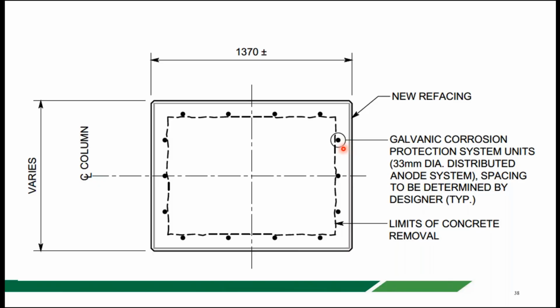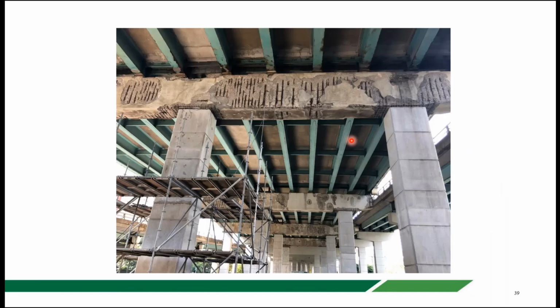They're putting some galvanic anodes in a vertical orientation on the columns and in a horizontal orientation on the pier caps. And then they're forming and pouring the concrete back to slightly larger than the original dimensions, but effectively they look the same as before when they're done. It's about 1/2 inch bigger in each direction. And so just to show you what this looks like during the work, here's a picture taken during construction. You can see the column here on the right and the column on the left.